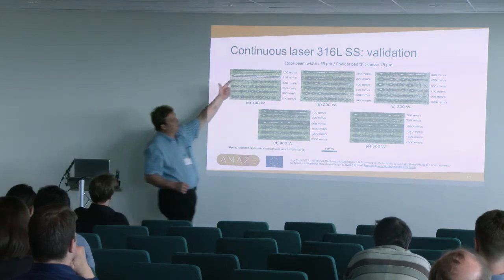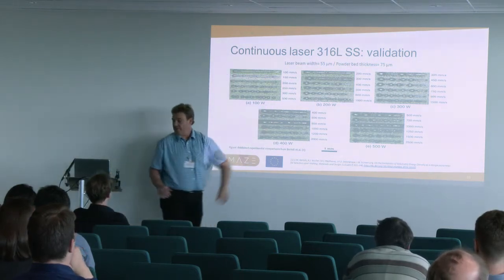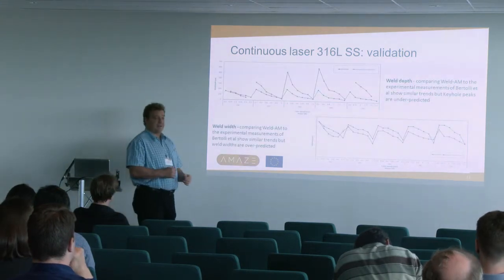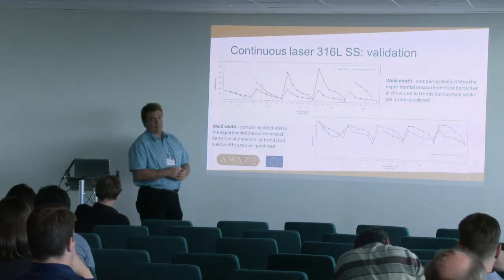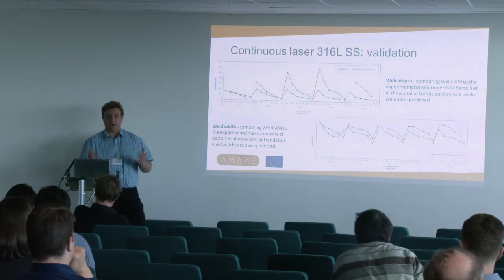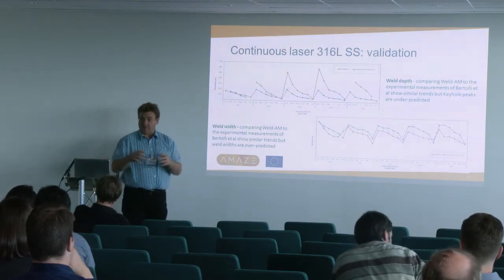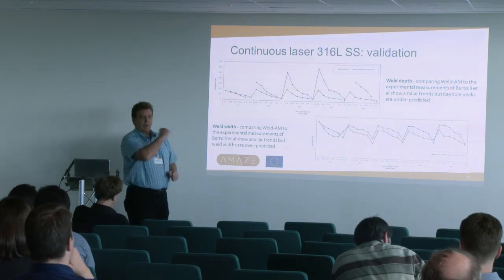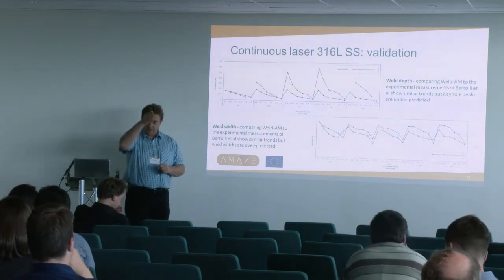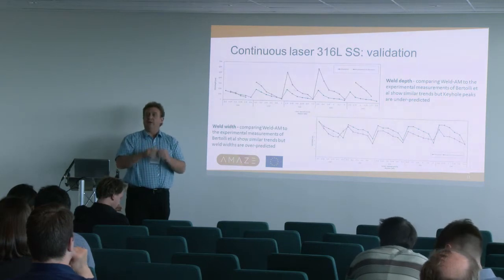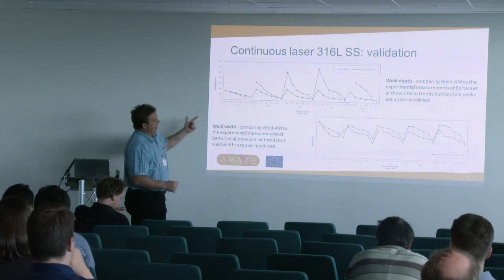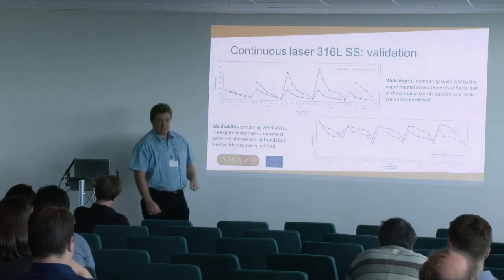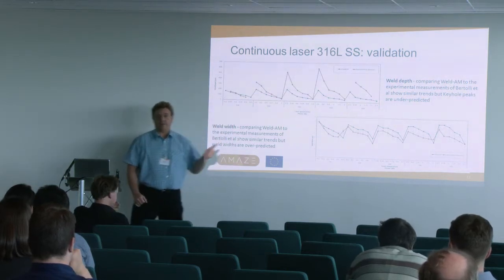You can see some continuous tracks, and you get breakups, which are due to the Plateau-Rayleigh instabilities, where the surface tension forces are weaker than the viscous forces, and it can't hold it together, and it breaks up into droplets. The good thing about that paper is that they've done all the measurements, they've cross-sectioned it, they've got the depth of the melt, they've got the width of the melt, and we can then compare it to our models. And they're not spot on, but the trends are being followed.